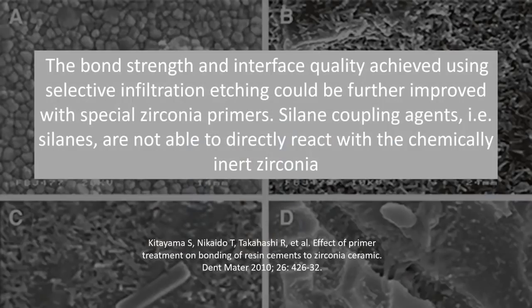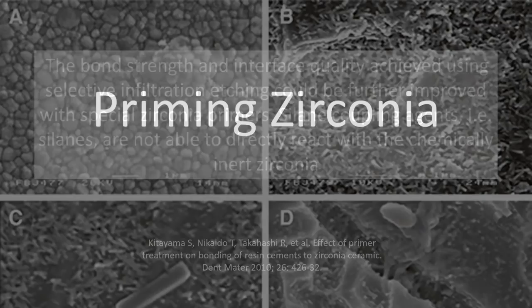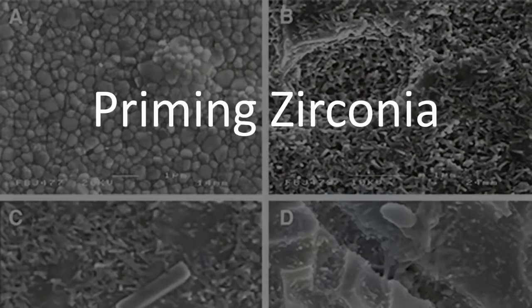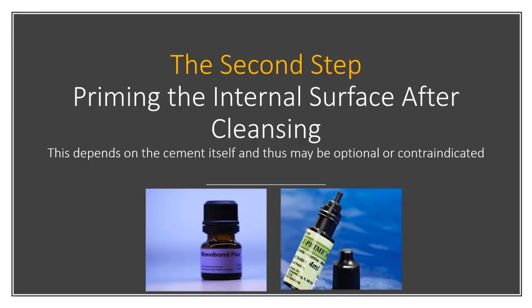The bond strength and interface quality achieved using selective infiltration could be further improved with zirconia primers or silane couplers. So now the question is, what do you use? The studies have really shown that for many of these cements, not all, you need to prime or silanate. So when you're priming zirconia, you can use something like Ivoclar Monobond Plus. You can use a Z Prime and other primers for zirconia. And again, it all depends on what you're doing.